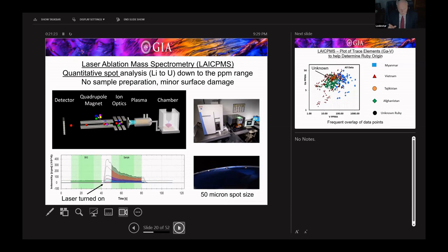You can detect all the naturally occurring elements down to the parts per million range, quantitative analysis. You don't need any sample preparation, but you do produce some minor surface damage. But of course, that can be repolished without too much difficulty.